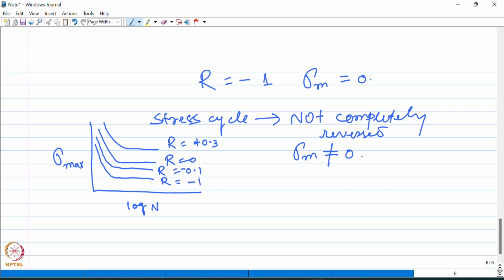So here you can note one thing. As the stress ratio becomes more positive, which is equivalent to increasing the mean stress, the measured fatigue limit increases. As you could see from here, the fatigue limit, that is the point at which it becomes horizontal, increases as the value of R becomes more positive. The other way of determining the fatigue life in this kind of loading condition, where it is not completely reversed, is by plotting the alternating stress sigma A against number of cycles to failure at a fixed value of mean stress.